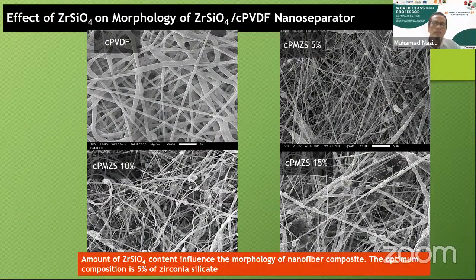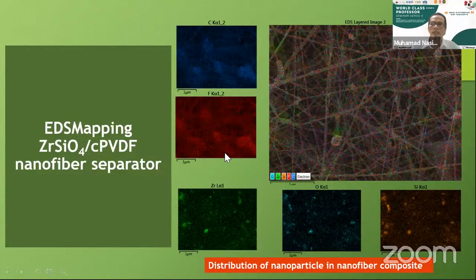Okay, this is the morphology of the separator. You can see here, this is the pristine co-PVDF separator. And when we add the zirconia silicate, the diameter of the fiber is decreased. And also we get the optimum composition is in the zirconia 5%. And then we measure the distribution of nanoparticle in the nanofiber composite by using EDS, same EDS.